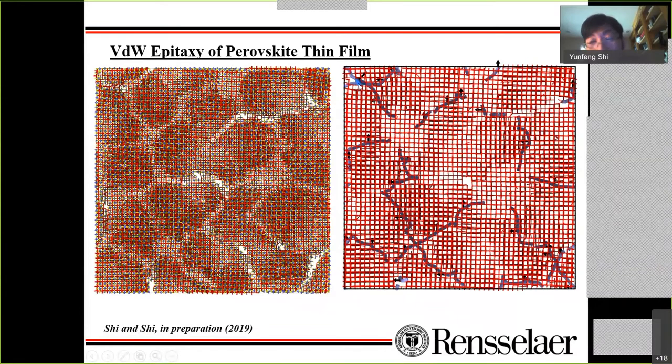Those dislocations are perpendicular to the substrate. You can see here, if you keep growing, the threading dislocation is coming out of the film, right? So it's not going away. This is very detrimental to the thin film quality. Here is a threading dislocation. I believe here is another one right here. You can see the little black arrow. Those are the dislocations' Burgers vector. So we can identify those as well.